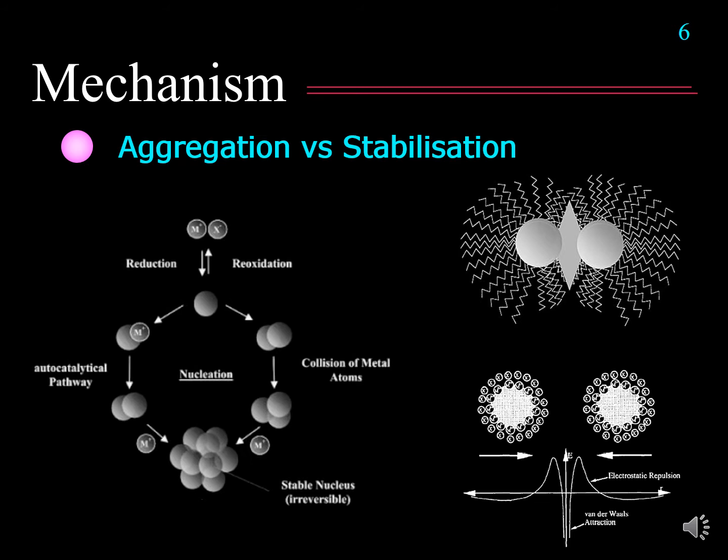The first mechanism, in the upper picture, is to cover the gold nanoparticles with polymers or any kind of long chain. Then we have steric hindrance, preventing the gold from aggregation. Another method is using the electrostatic repulsive force.